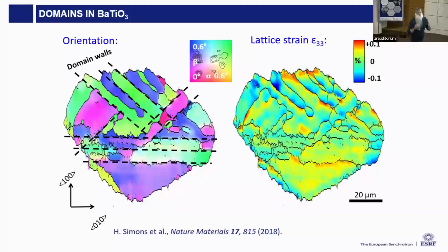And we actually see that the decay length of the strain fields is larger than the domain size, which means that the entire domain is strained. Strain breaks the lattice symmetry, so there's a lot of exclusion rules and preservation laws which are enforced by symmetry. They do not apply in a crystal that is fully strained throughout its whole volume.